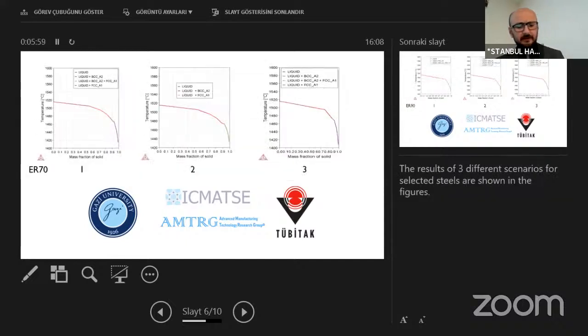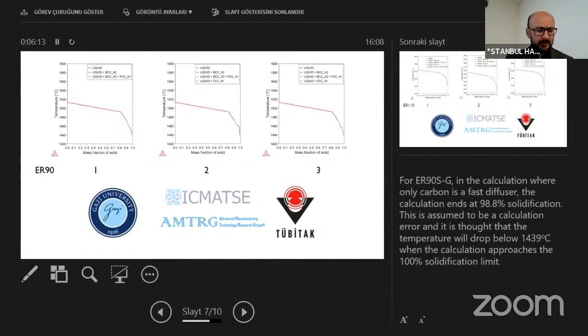The results of three different scenarios for selected steels are shown in the figures. This is for ER70-S-A1 steel. For ER90S-G, in the calculation where only carbon is a fast diffuser, the calculation ends at 98.8% solidification. This is assumed to be a calculation error, and it is thought that the temperature will drop below 1439 degrees Celsius when the calculation approaches the 100% solidification limit.